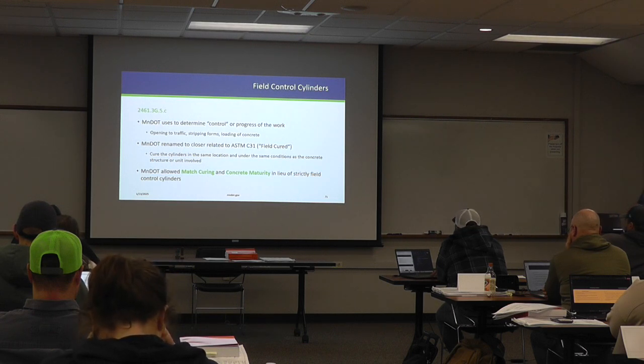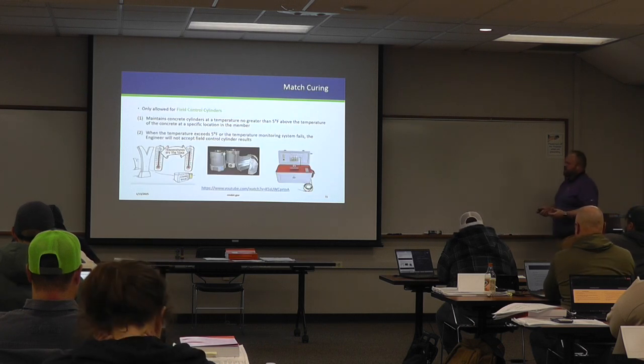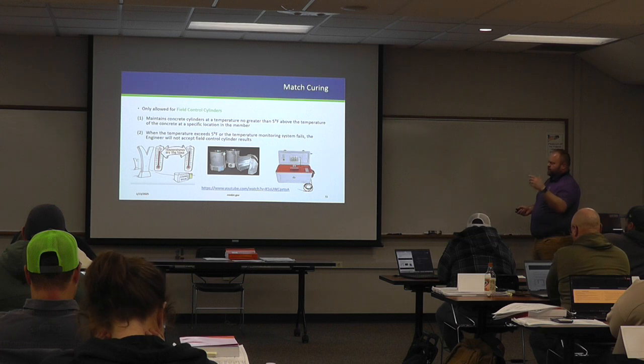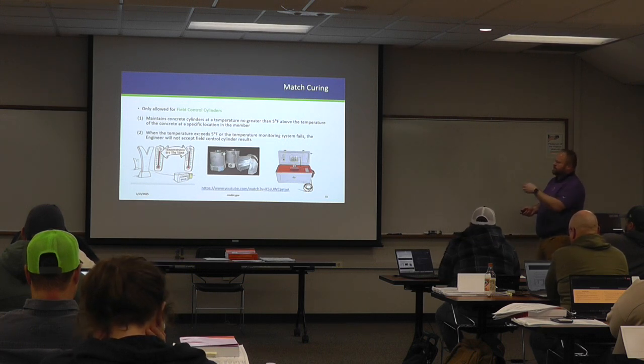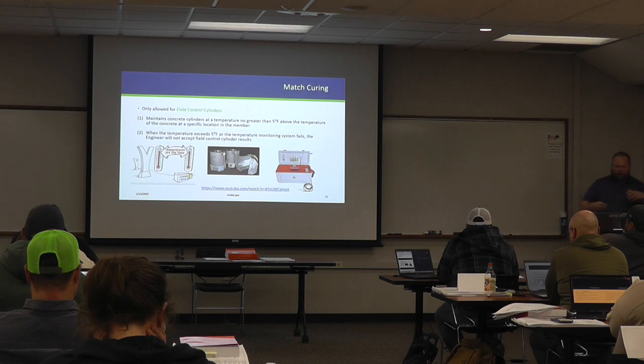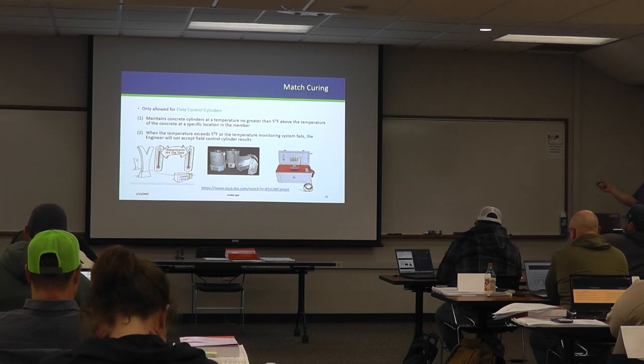There are other things like match curing and concrete maturity that are a little bit better at mimicking those conditions than just putting a cylinder next to your pour. And so what match curing is, you basically have a cooler that's got a computer that's linked to a sensor in the element that we're thinking of for temperature, and it's keeping that water that the cylinder is in at the same temperature of the element that we're wondering the strengths about.